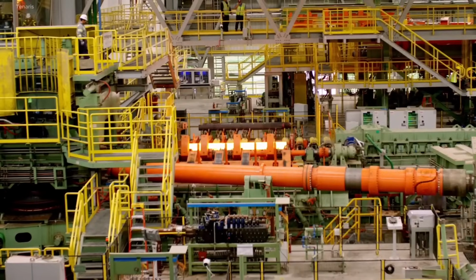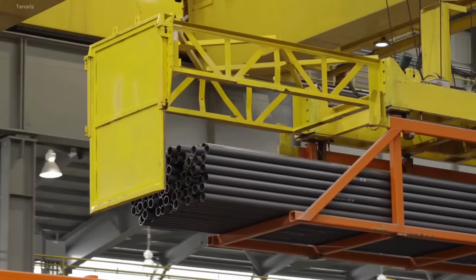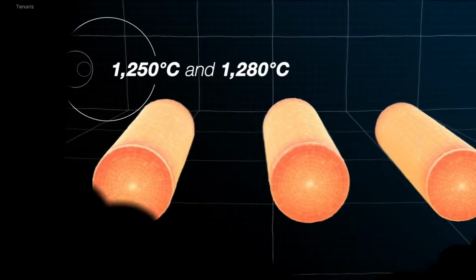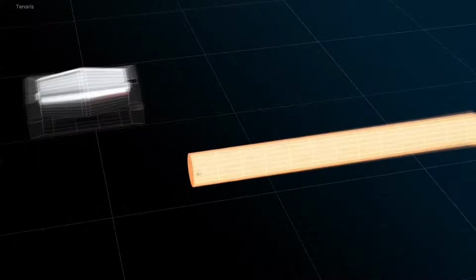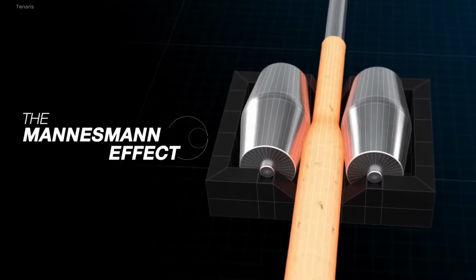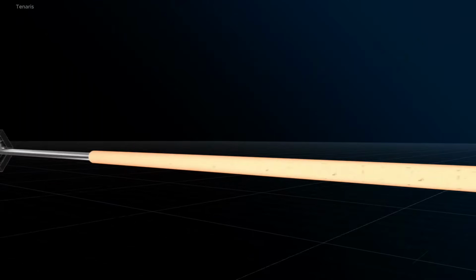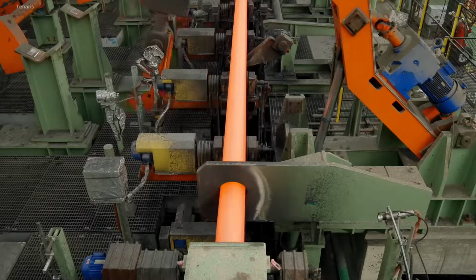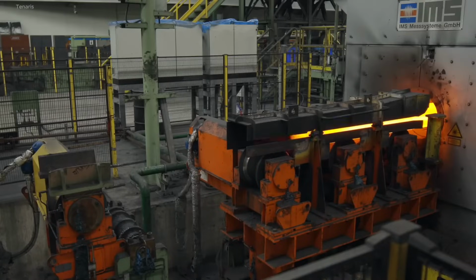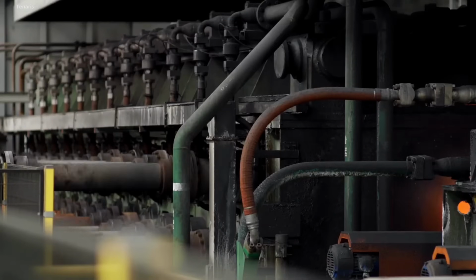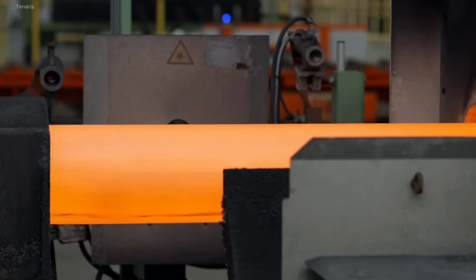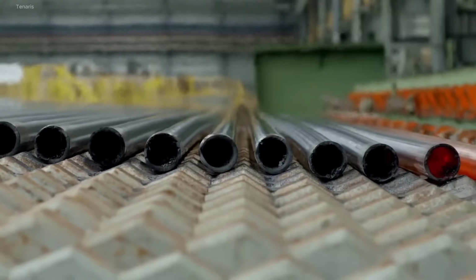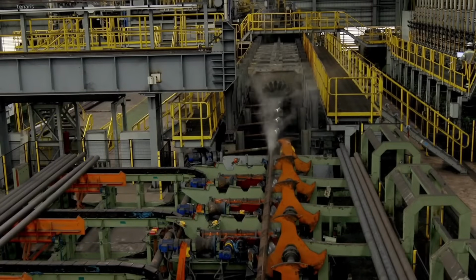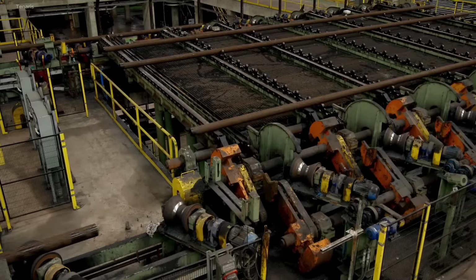Tenaris Bay City's seamless pipe manufacturing process combines advanced automation with metallurgical precision. Production begins with steel bars cut into billets of precise weight, then heated to 1250 to 1280 degrees Celsius in a natural gas-powered rotary hearth furnace. These billets are pierced into hollow blooms using a barrel-type piercer, leveraging the Mannesmann effect. The blooms are elongated in a finishing mill, reheated via induction, and diameter reduced in a stretch-reducing mill.